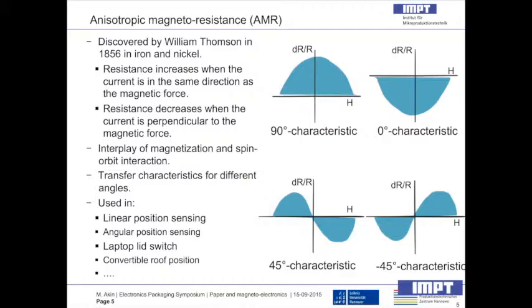And then he applied the magnetic field perpendicular to the electric current on the iron bar, and he measured a decrease in electrical resistance. So basically that was his discovery, and he found out the same phenomenon happening in nickel. So iron and nickel happen to be ferromagnetic materials where the interplay of magnetization and spin-orbit interaction make this change in electrical resistance depending on the angle between electric current and magnetic force happen.